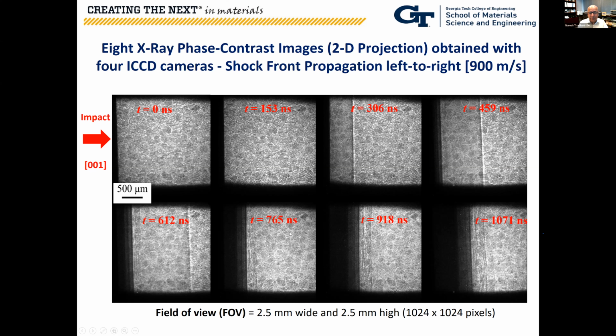By the time you get to 765 nanoseconds, that shock front has propagated through that entire span of the field of view, which was approximately 2.5 millimeters of the sample we are viewing, although the entire sample length is about 6 millimeters. At later times, we don't see that shock front, but we do see the disturbance of the particles as they are being disturbed behind it.